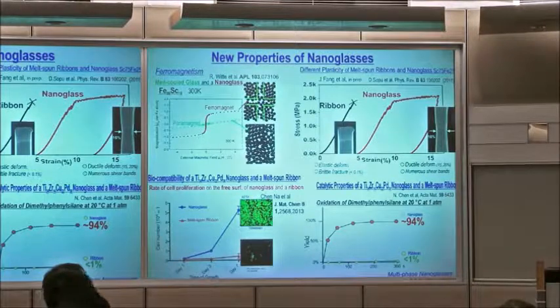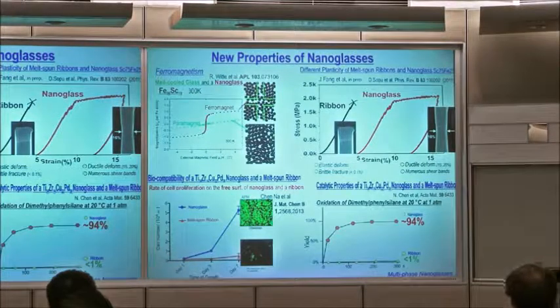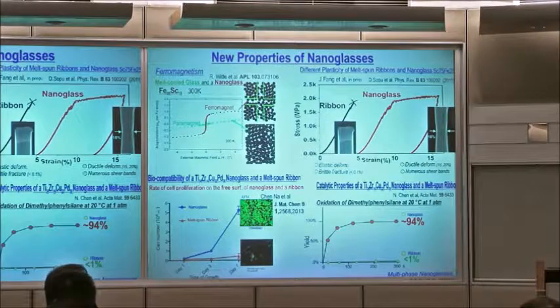But what he says is, if I don't change the chemistry, I only change the size and the spacing of the particles, cells are very sensitive to that. Certain spacing, certain sizes make the cell grow very rapidly. And we seem to get a somewhat similar answer. Because one has to keep in mind, when you have this nanoglass, it's electronically a variation on a few nanometers electronic structure. So it's chemically the same element, but it's a different electronic structure. And that's apparently what the cell sees.